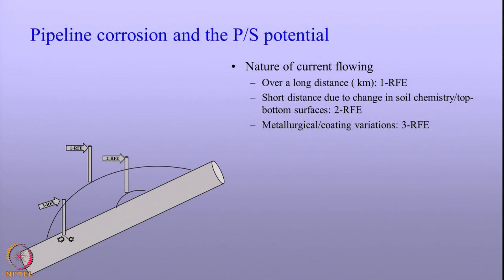On the other hand, if the reference electrode is kept right over the pipeline, very close by, then you will see that the current flowing due to metallurgical variations and the coatings generates a voltage that is measured. So, the potentials measured at the three locations give three different types of information. The potential is always measured with respect to the electrolyte. Of course, you connect the reference electrode to the positive terminal of the voltmeter, and the negative terminal of the voltmeter is connected to the pipeline.